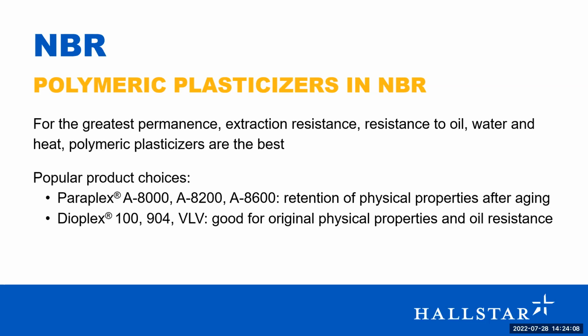So not only do you get the physical properties that you're looking to start with, but you're maintaining those properties after plasticizer has been extracted from oil or heat or temperature. With a monomeric ester chemistry, all of that plasticizer will be removed with heat or oil, and you'll see it in the weight loss. With these sort of chemistries, you'll see very, very little weight loss. And so you'll be able to retain a lot of those tensile properties that you're looking for.